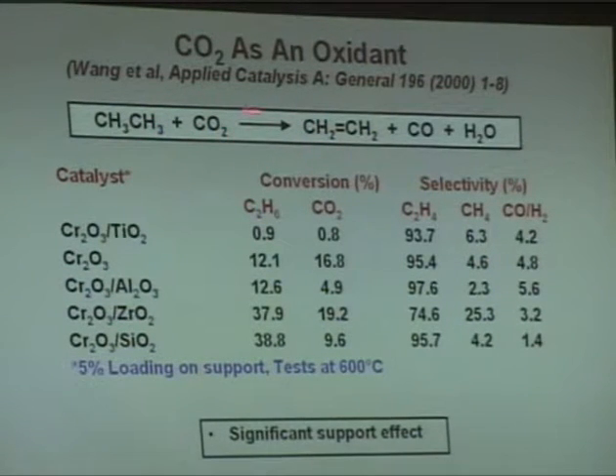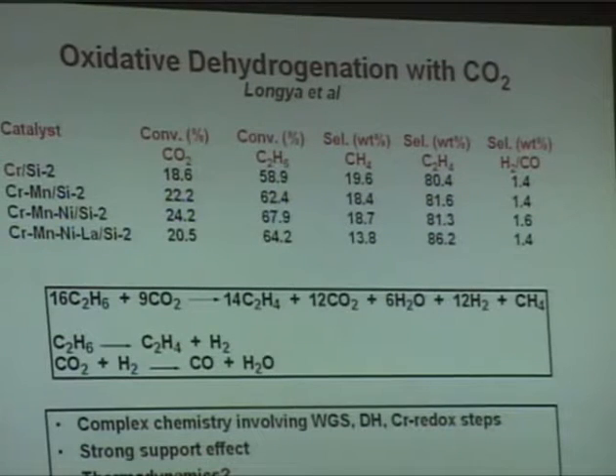It's possible to do an oxidative dehydrogenation of ethane with carbon dioxide and generate ethylene with pretty decent selectivities, over 90% selectivity to ethylene at pretty decent conversions. In the case of chromium-3 on silica, which is the best catalyst, around 38% conversion of the ethane with 95% selectivity to ethylene. Now, you say to yourself, there's something wrong with this. This is thermodynamically not right. That's your first instinct. Well, I've shown here some additional results.